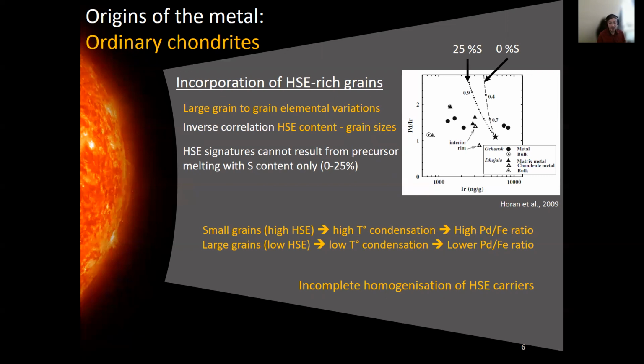Working in favor of incorporation, a study of Horan and collaborators in 2009 has shown an inverse correlation between highly siderophile element content and the grain size, which cannot be explained by the melting of a metal precursor with 0 to 25% of sulfur, as highlighted in the diagram on the right. They also found a lack of correlation between highly and moderately siderophile elements within metal grains, arguing in favor of the incomplete homogenization of refractory phase within metal grains. In addition, they demonstrate that compared to large metal grains, small ones have a high palladium on iron ratio, pointing out condensation at high temperature.